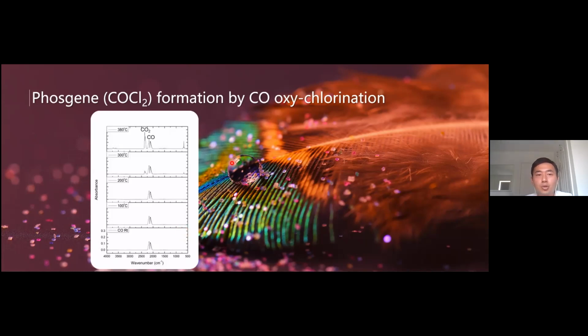We always found that the project doesn't go well from the beginning, and so was mine. By increasing the temperature and the gas flow of CO and HCl, we could see that at the reaction temperature, actually only carbon dioxide was formed. So it tells us that the catalyst doesn't work.